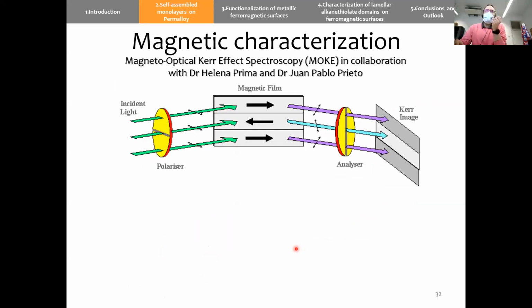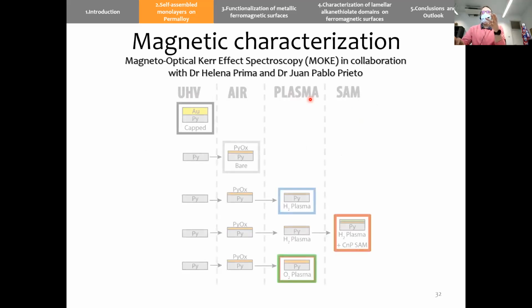We also performed some magnetic measurements using the magneto-optical Kerr effect, which is an equivalent technique to SQUID, but it uses light in the presence of an external magnetic field and studies the changes of the polarization of the incident light. And with this, we can reconstruct the magnetic hysteresis on the surface we are studying.